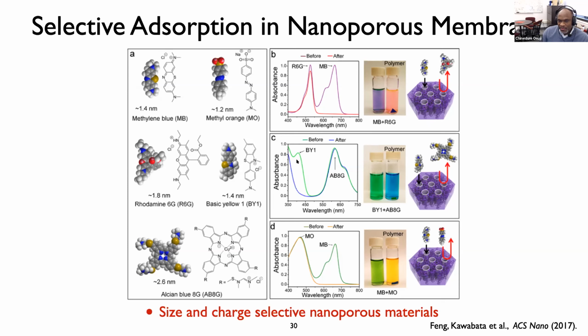And the same thing is seen here with basic yellow versus an Alcian blue dye, which in this case is much bigger. And then finally, we look at the case of, say, methyl orange, which is absorbing down here sort of in the blue-green, and methylene blue. The methylene blue goes into the polymer and the methyl orange stays out. In this case, methyl orange is a smaller dye than methylene blue, but the methyl orange stays out because it's a negatively charged species, and the pore walls that are produced in these membranes are left with a negative charge on them after the processing.